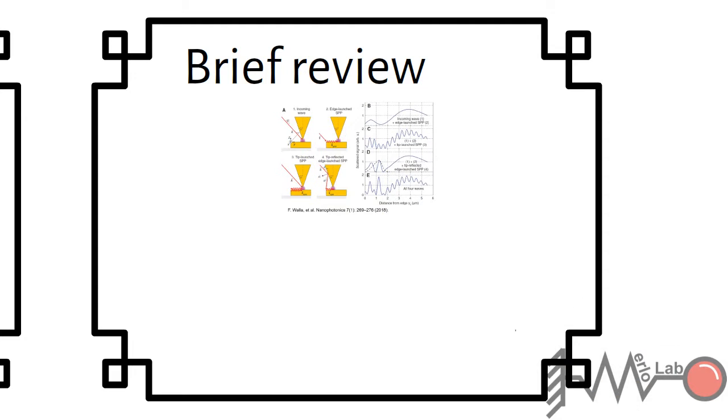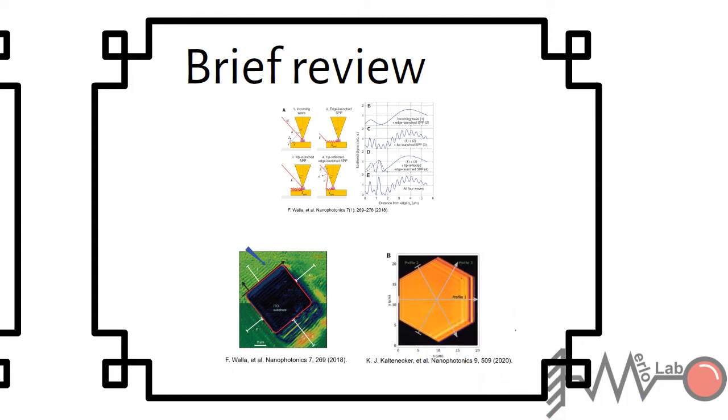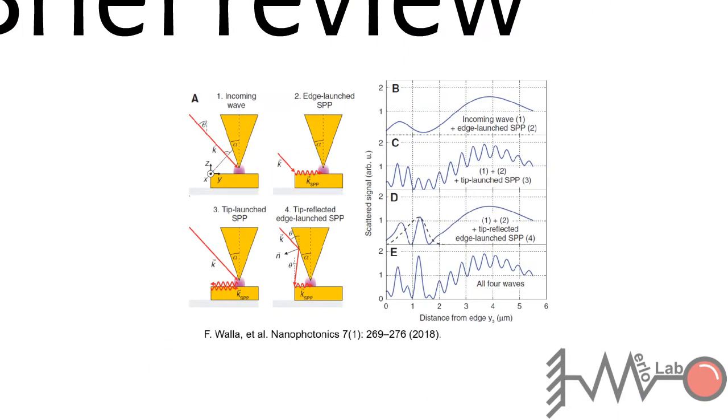Interestingly, the near-field microscope in scattering configuration has been used for the detection and analysis of surface plasmon polaritons in metallic surfaces and 2D materials. However, there is evidence that suggests the existence of important artifacts due to the interactions of different components of the electromagnetic field, not necessarily related to the surface plasmon polaritons fields. It means that far-field components are contributing to the overall measurement.